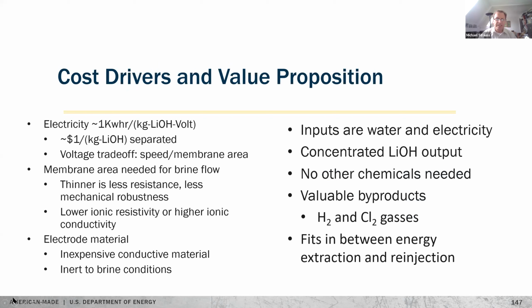The cost drivers are basically three things: electricity, membrane, and electrodes. The electricity use is basically 1 kilowatt hour per kilogram of lithium hydroxide produced per driving volt. We're going to assume that we run this at 5 volts. So that's basically $1 per kilogram of lithium hydroxide, at 20 cents a kilowatt hour, which is standard for California. But we figure this should actually be less because we're doing this at a power plant, so we should be getting behind the meter pricing without the transmission and distribution. So more likely around 60 cents per kilogram of lithium hydroxide. This compares well with the current price of lithium hydroxide, which goes between 60 and 70 dollars a kilogram, FOB China. Higher voltages are used because less membrane material is needed.